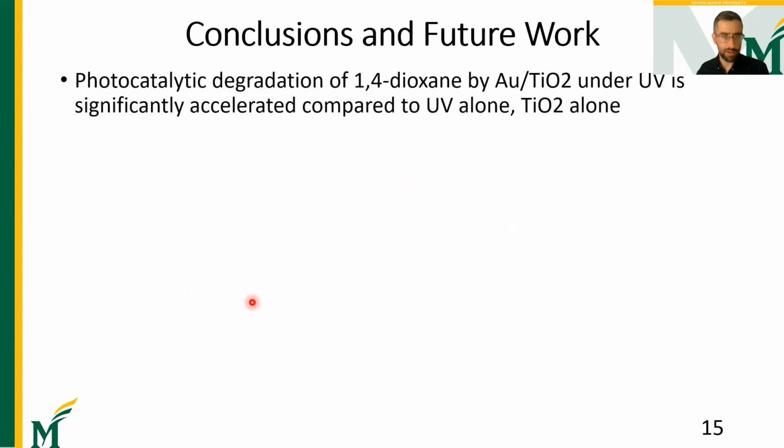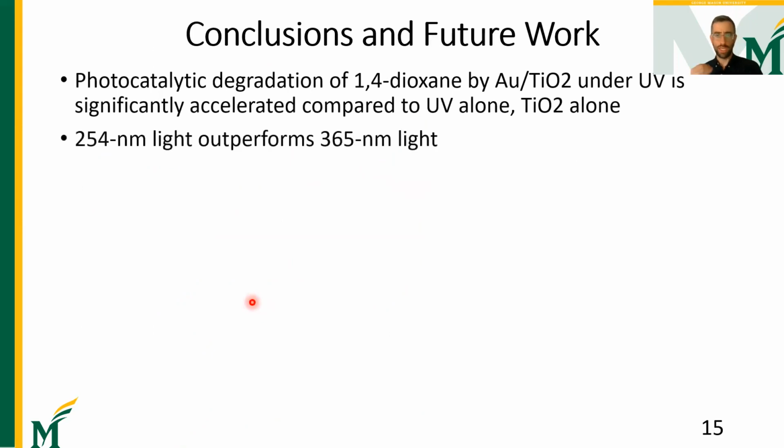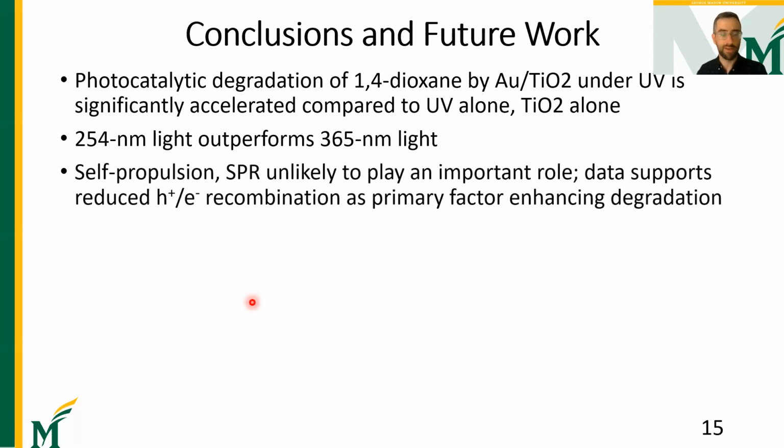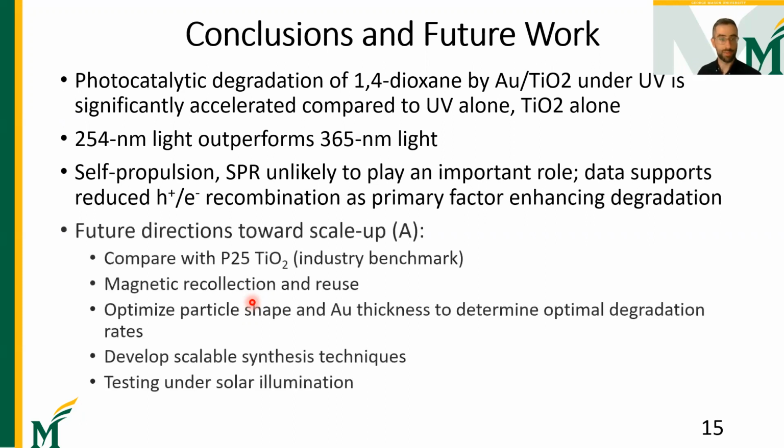In conclusion, the degradation is improved using gold-coated TiO2 particles. 254 nanometer light indeed outperforms 365. Self-propulsion is unlikely to play an important role because it's unchanged in salty conditions. And SPR is unlikely to play a role as well, because again, we're looking only at UV light here, and SPR is generally important in the visible range of the spectrum.